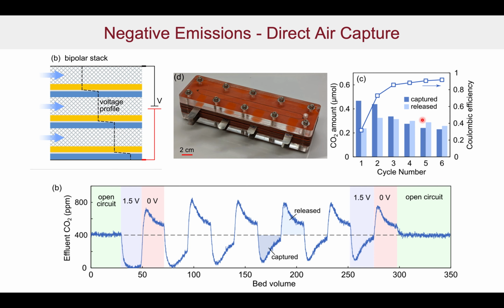After a certain period of time, about 5 or 6 cycles, we start to level out, and we can see that we've got a very stable cyclic process. Again, the coulombic efficiency, and this is for looking at ambient air conditions at 400 ppm, is around 90 to 95%, which is really very efficient.